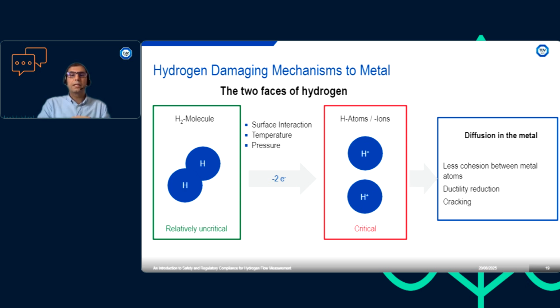So when they diffuse into the structure of the material, they can go between the atoms of the metal and then reduce the cohesion between metal atoms. That will cause ductility reduction in the metal, and then finally it can cause cracking in the metal and the material will fail quicker. So if you are using a system with hydrogen, it is more likely that your system or your system components fail quicker than if you are using the same system with, for example, natural gas.